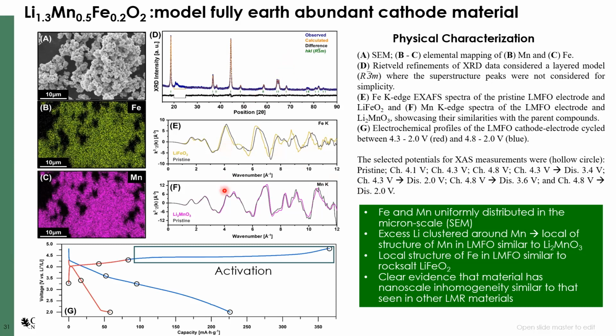However, if you look at it with X-ray absorption, looking at the local structure around manganese and iron, we can clearly show that this material on a local scale is not homogeneous. There are regions which are rich in lithium and manganese. By local regions, I'm talking of regions of the order of 5 to 10 angstroms, 1 nanometer length scale. These materials tend to phase separate. Maybe phase separate is not the right word. It's just that they are not homogeneously distributed. There is a lot of heterogeneity in it. But this is fundamental to these lithium-rich materials, which we have seen in many, many systems.